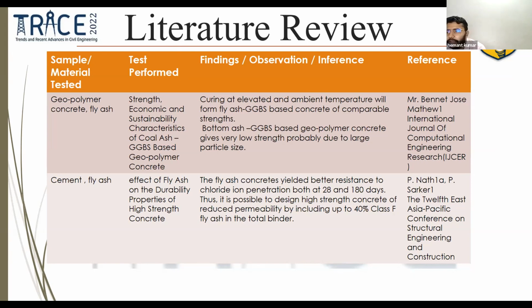Sample material tested: cement, fly ash. Test performed: effect of fly ash on durability properties of high strength concrete. Findings: the fly ash concrete yielded better resistance to chloride penetration both at 28 and 180 days. Thus, it is possible to design high strength concrete of reduced permeability by including up to 40% class F fly ash in the total binder. Reference: P. Nath, P. Sarkar, the 12th East Asia Pacific Conference on Structural Engineering and Construction.